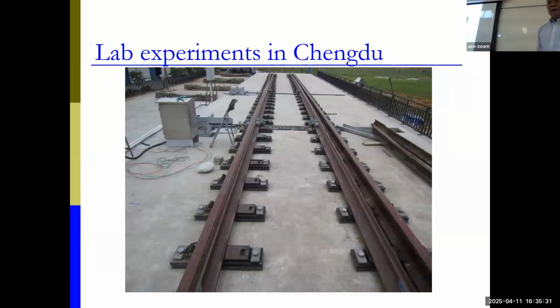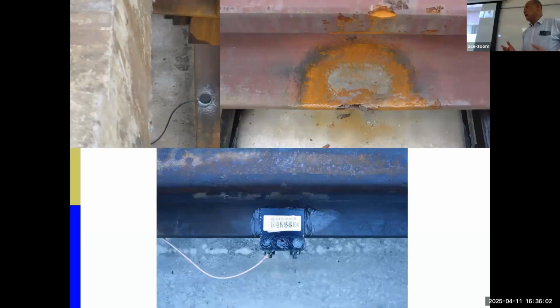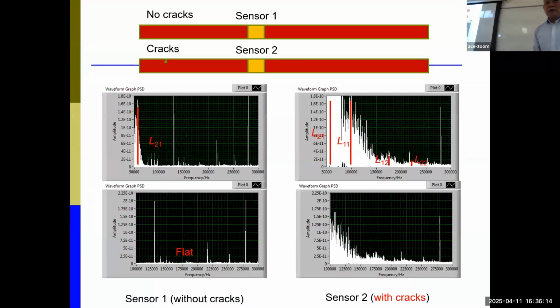And also we utilize this for high-speed rail crack detection, because high-speed rail has very long continuous welded track, 80 to 100 meters. So they are very afraid that any crack will create a safety problem. This was originally a project with Xinan Jiaoda and PolyU, and they met a lot of difficulty. They called me, so I said, okay, we can use our transducer to try. And then we put the transducer on, and we found it's really very good.